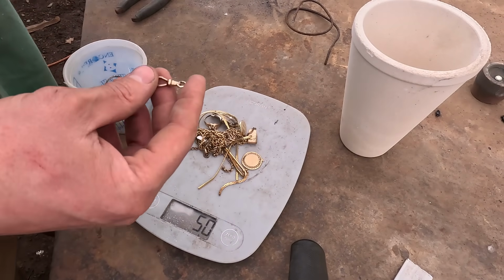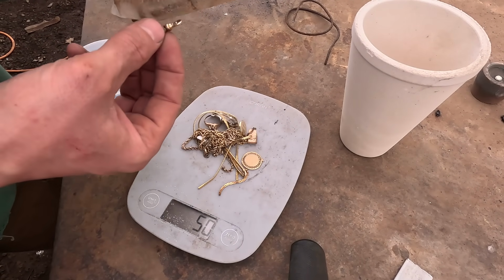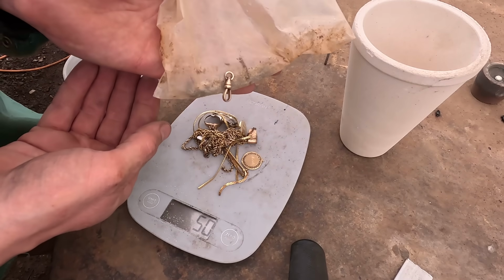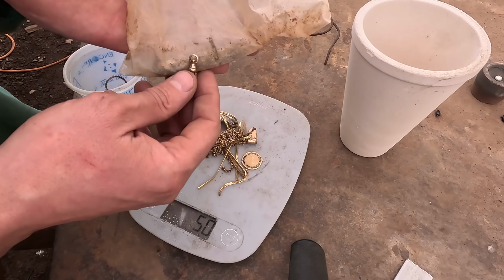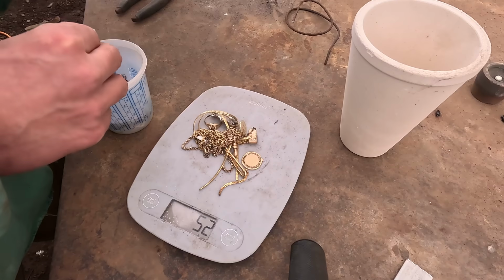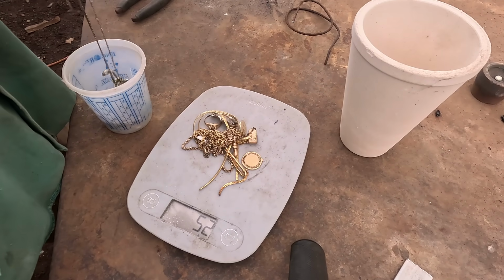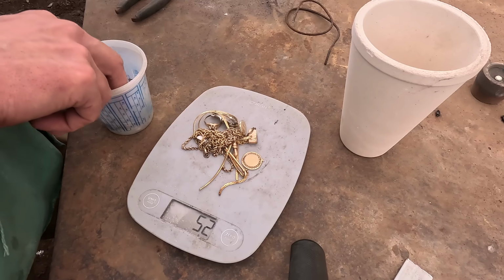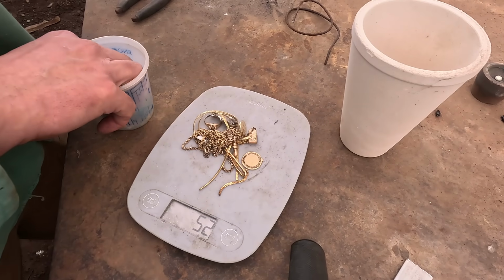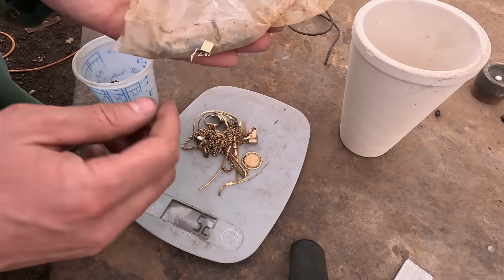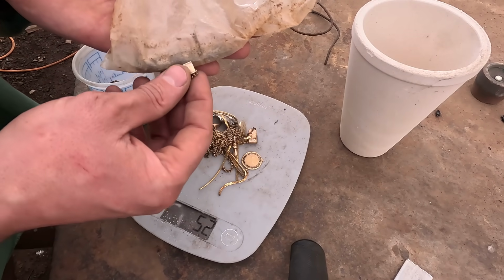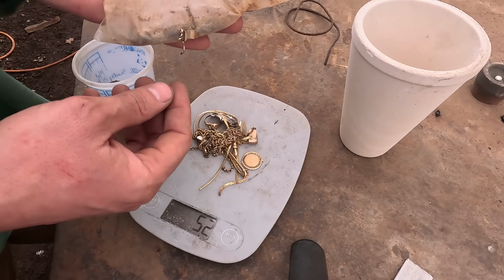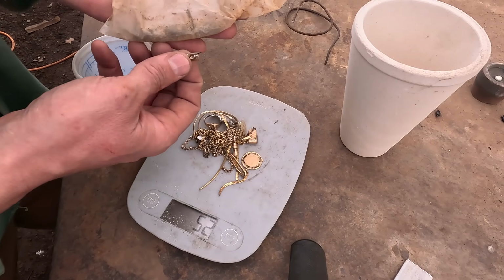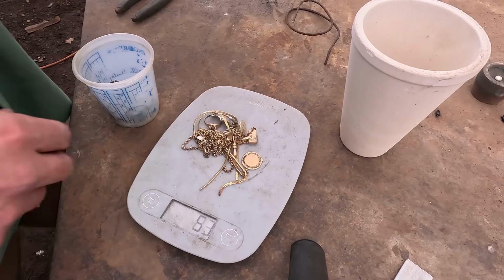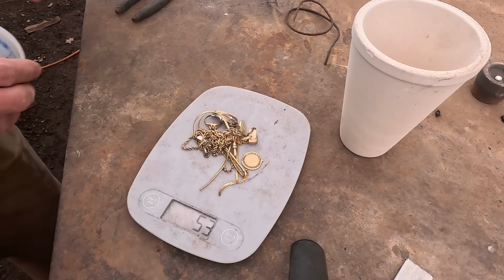One of the issues with gold fill is that a lot of these little clasps and stuff are magnetic. There you go. They've got little pieces of steel in them, and if you use the nitric method, the steel really causes you problems. So I started going through and clipping off all this steel, if I can get a piece of it, because I was originally going to use the nitric method, but I hope this new method that I keep alluding to will work even with the steel. So I'm going to put a few pieces of steel in there, so our new weight is 53 grams.